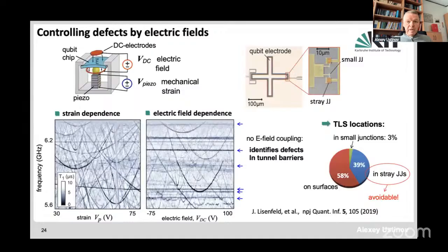Now, here is the result of this statistics. We see defects on the surfaces in the order of more than half. Then the defects in the junction are only a small fraction, about 3%. And typically in the tunnel barrier of the junction, we observe only roughly one defect, less than one defect per gigahertz. However, we discovered that there are many small weakly coupled defects in this circuit, which do not react to the external fields.